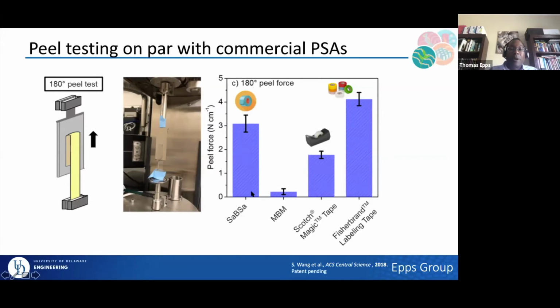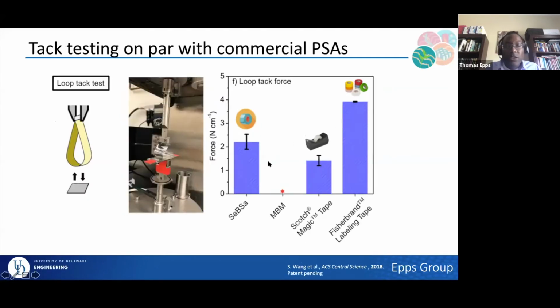I will mention that our bio-based material has no tackifiers, no additives, pure block copolymer, and we believe, in some work that I'm not going to show here today, that we get that adhesion and that additional surface energy enhancement from having the methoxy groups on these materials, which promote adhesion to things like the glass slides, etc. But the key point here is that we're right in the ballpark of Scotch tape and things like Fisher brand labeling tape. We can do other tests as well.